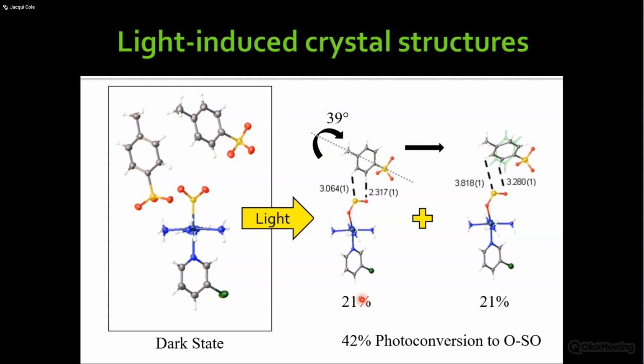And in this particular case, there was some symmetry involved, as you can see from the suspicious 21 and 21% photo conversion. We managed to isolate this because 21% did rotate and then 21% didn't, out of the photo converted species, which was in total 42%, right? So 42% of the sulfur dioxide ligands actually photoconverted. The other amount stayed in the dark state.